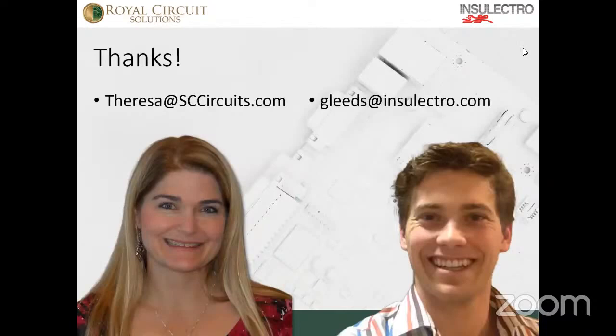From Seth Giles, when speaking of the resting position of a rigid flex PCB, is it possible to design the flexible position so that it is pre-tensioned to rest at, say, a 90-degree angle? So you can actually build in and form the flexible cable to a 90-degree bend. It's done post-processing. So once you've built your flexible board, we'll actually make a fixture, and then that fixture will be laminated at not as high a lamination temperature as we would use to cure the B-stage acrylics. But it'll soften up the material during that modified lamination cycle, and then as we cool it, it'll set that position into the flexible cable.